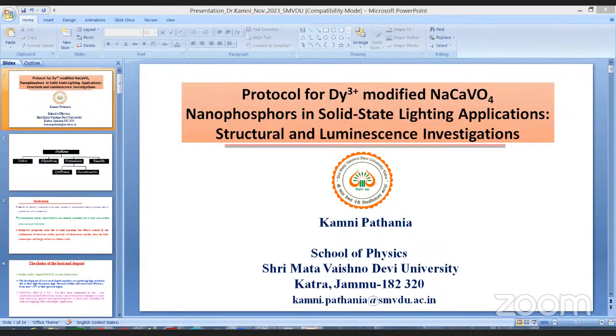Results and discussions. So the first thing we want to see is whether the dopant we are taking, in our case the dysprosium 3+ ion as the rare earth dopant, will substitute which ion in our host matrix. For that we have to calculate the percentage difference ratio between the substituted and the host ion. So in this case, we have seen that the atomic radii of the sodium.